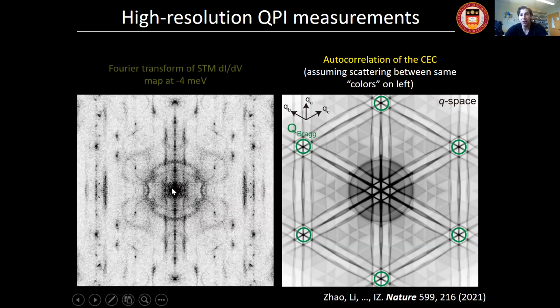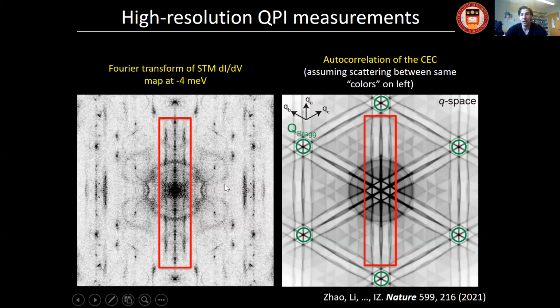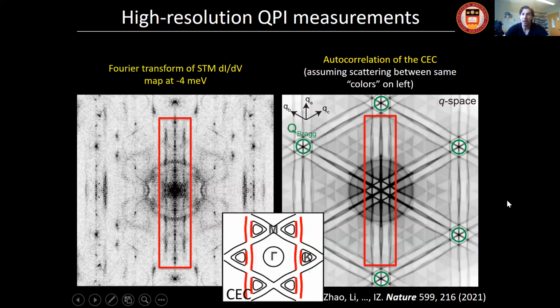So if we look at what STM sees, well, you're going to observe some similarities and some differences. So we indeed see this kind of threefold feature near the center. You're going to see this threefold feature at the corner, but that only exists along one particular direction. Okay, so this feature is very similar, but the other two lattice directions are simply notably not there. So there is also this kind of C2 symmetric quasi-particle interference fingerprint that, again, we can directly see comes from these bands highlighted by red.